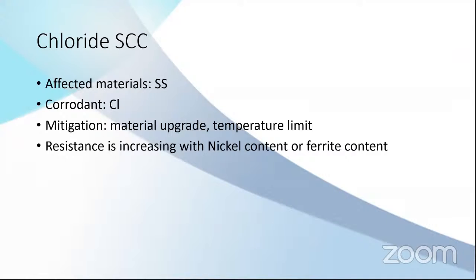Increasing nickel content or ferrite content is increasing the resistance to chloride. That's why nickel alloys normally is considered very resistant to chloride stress corrosion cracking. And duplex material, where you have high ferrite content, or ferritic stainless steel, is also considered very resistant to chloride stress corrosion cracking. When I say resistant, it is highly resistant, but not immune. In a very high temperature or very high chloride content, some of this material can still crack, but you need very, very high parameter variables for that. But normally you don't find it in the actual application.